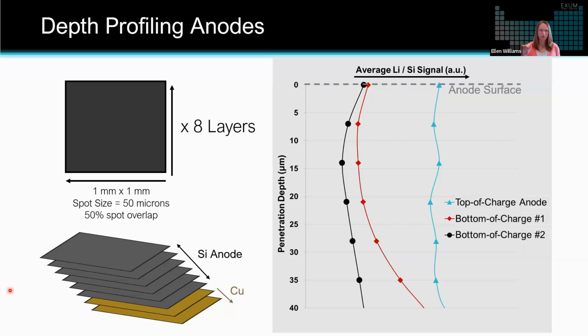So you can see on the top, that's that surface layer, and then each of those data points is the subsequent layers, where, again, we're looking at that average lithium to silicon signal with higher on the right. You can see the copper current collector occurring at about 40 microns, that 7th and 8th layer here. So first, I want to draw your attention to the blue data points and line here. So those data points were acquired on that top of charge anode.